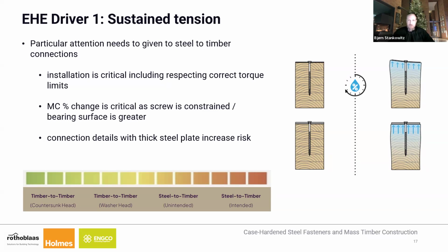So when we look at construction sites, we have to look into fixing these screws into thick steel plates. Obviously need to be more cautious and more risk averse to the introduction of moisture and trapping moisture below it to reduce that. There are ways to add some layers in between steel plate and the timber if we cannot mitigate the risk of the moisture getting there. And in terms of a rubber mounting that will compensate for some of the pressure and dissipate this. Other options, obviously, to lift the steel plate and allow for some circulation of air underneath it to avoid the moisture increase in the timber itself, but more to that later.